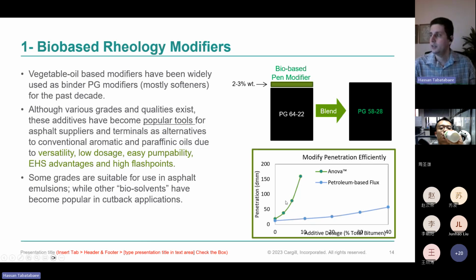When you look at the penetration, you can see the same type of range, where going from 0 to 10% of a bioadditive can have much more of an impact on penetration than a flux oil might have. And for this reason, these have become quite popular in a lot of places for modification of asphalt binders and creating softer bitumen grades.